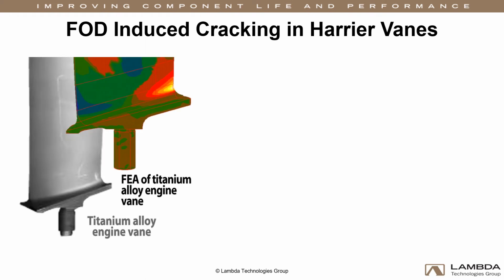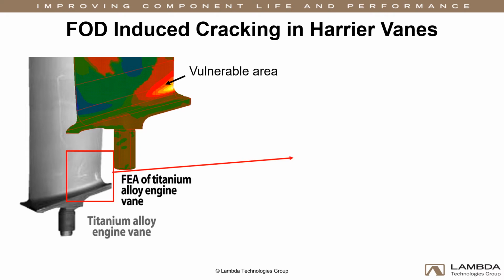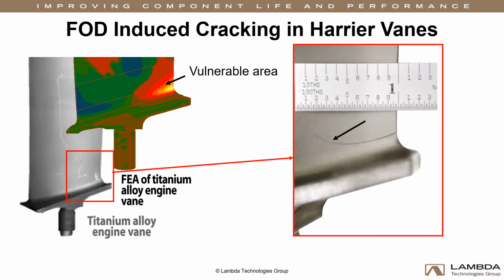The first-stage low-pressure compressor vanes in these engines were prone to failure from cracks in the inboard trailing edge of the airfoil near the platform. Several Class A mishaps involving the loss of pilots and aircraft have been attributed to fatigue failure of this vane.